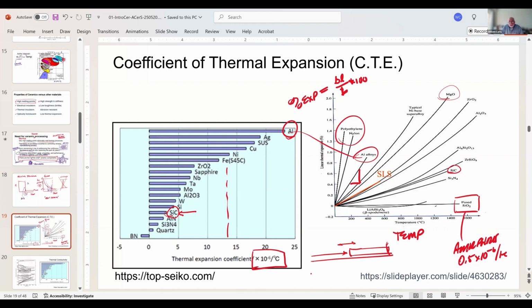There's another material called beta eucryptite, which has a negative thermal expansion coefficient. It's a lithium aluminosilicate. It shows up in Corningware, for example, the blue flower, white casserole dishes. It has a negative thermal expansion coefficient. That's called a glass ceramic. So you have that crystal in a glass matrix, and the ratio of the glass to that crystal gives the overall component a zero thermal expansion coefficient, which gives us good thermal shock resistance.